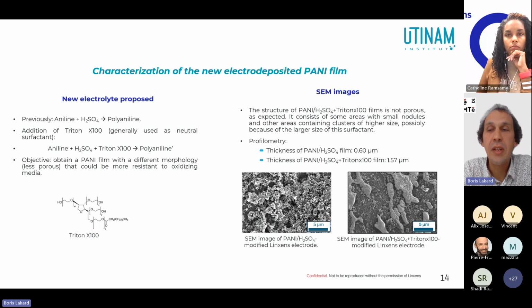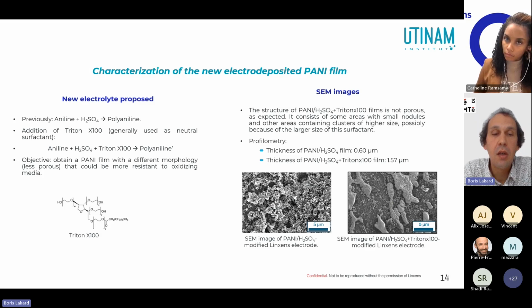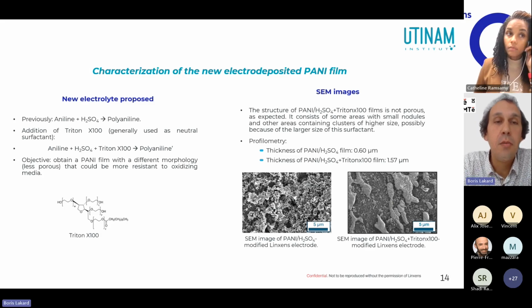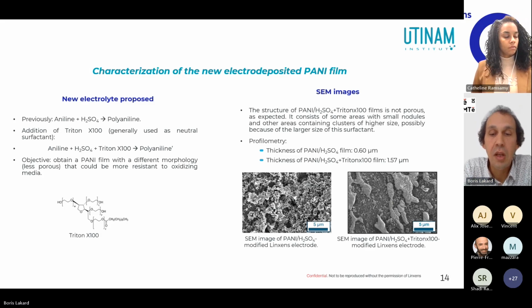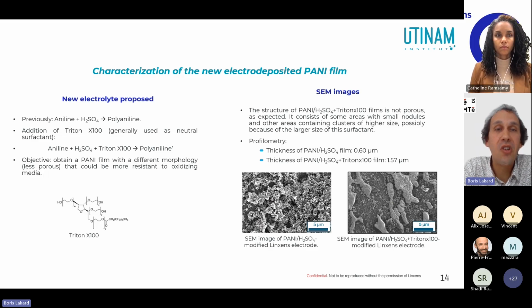So we have then made other images by electron microscopy. On the right, you can see the morphology of the new polymer film containing Triton, and you can see that it's very different from the one obtained previously. It's notably much more compact. Also, the film thickness is different because with this new electrolyte, we have obtained a thickness of 1.6 micrometer, so a thicker one.